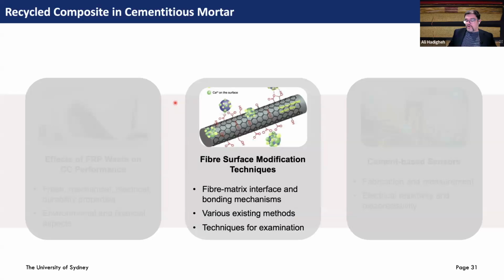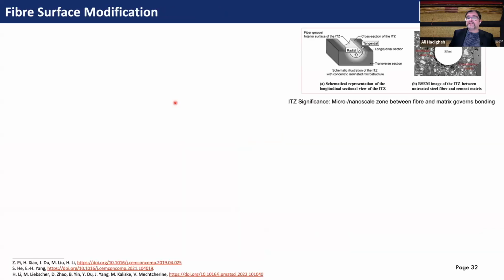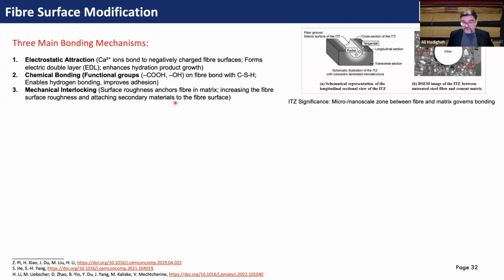But the second part of our work, as I said, that dispersion is extremely important and critical. So how can we improve that dispersion? Why is dispersion important? Why is surface modification important? Because basically the interaction between fiber and cementitious material is through that interfacial transition zone. And if the transfer of the load is happening through that ITZ, if we have a very strong, robust ITZ, you have very good performance from your cementitious material.